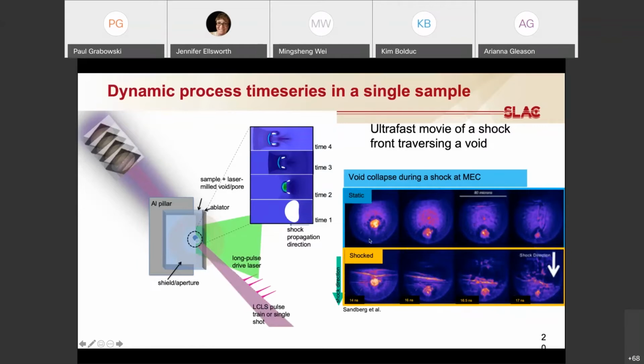Each of these images are pairs, so top and bottom is a pair in each time slice case. And each sample is different because in Richard's work here, we're not using the pulse train. And so you can see there's a number of interesting features, sort of hard to identify what's going on. We've got a few bright lines that show up. I think we've identified this is probably the main shock coming through. The void is somewhat modified, but this is a messy case.